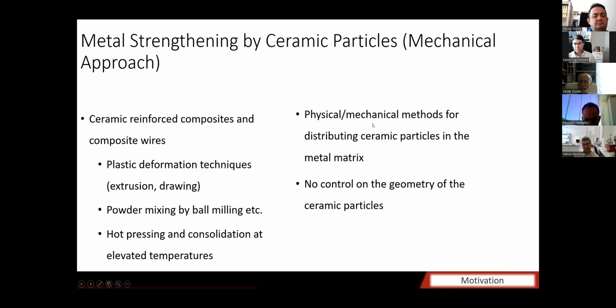They use physical or mechanical methods to distribute the ceramic particles in the metal matrix. But because the ceramic particles are really hard, these methods only help in distributing, and the most work they do is on the matrix because they plastically deform the matrix, and they cannot do it with the ceramic particles. So they do not have a good control on the geometry of the ceramic particles inside.